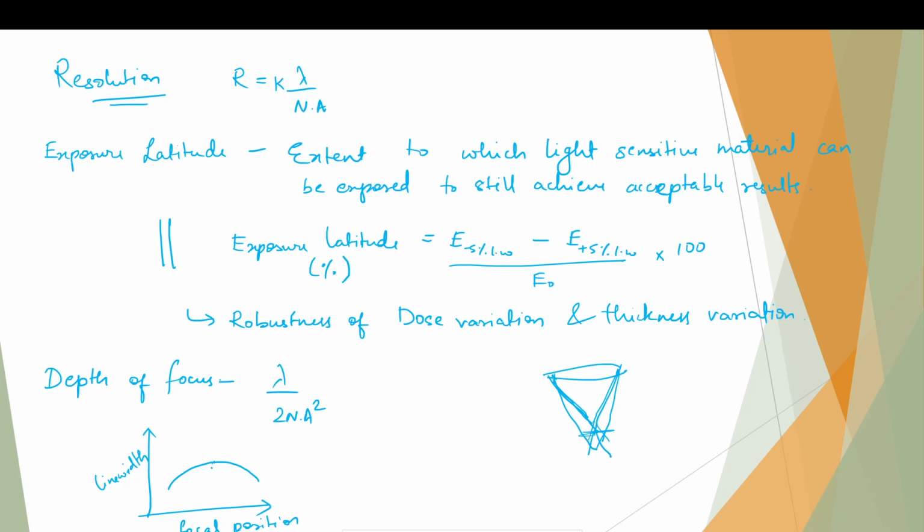So this line width versus focal position also depends on the dose that we give. Just like I said here, the dose will change the line width, right? So say this is at some dose E1, at a different dose I'll get a different curve, and at a third dose I'll get a different curve. So there will be some line width tolerance that I can give.